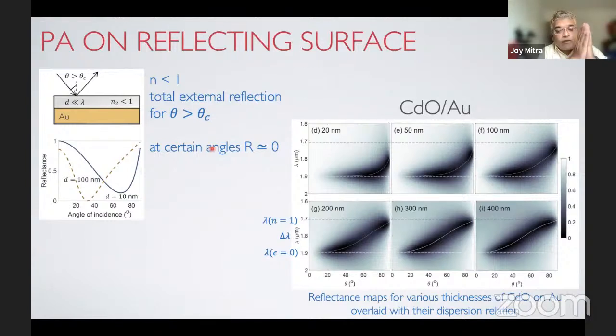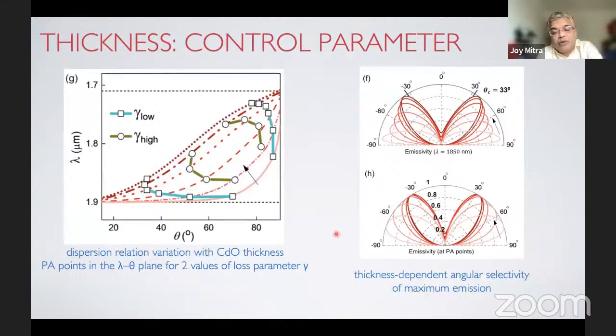Now, there is a detailed understanding, which we have in our publication, of why these things actually happen. But within this wavelength range, where n is equal to 1 and epsilon goes to 0, this delta lambda, we see these strange properties. To cut a long story short, as a function of wavelength, the direction of maximal emission changes with thickness. So we can establish that thickness is a very easy control parameter for thin film coatings. If you change the thin film thickness, immediately they start emitting in various different directions.